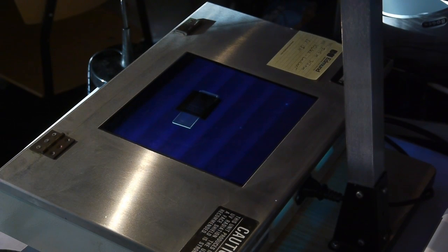I calculated this to have somewhere about 20 milliwatts per square cm of UV at the surface. That should be enough to expose the slide in about 30 seconds or even less, probably more like 10 seconds. But I leave it on for about 30 seconds to a minute just to be sure.